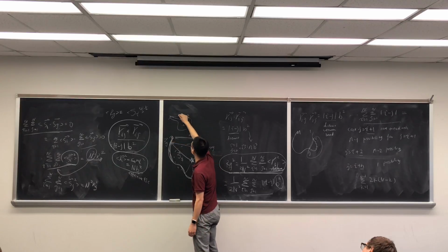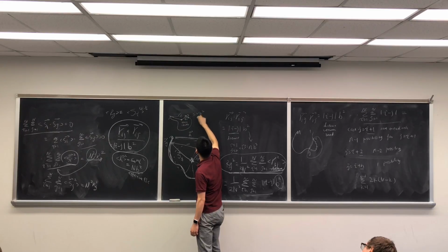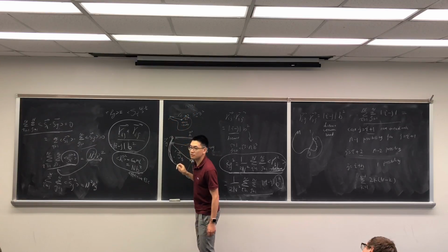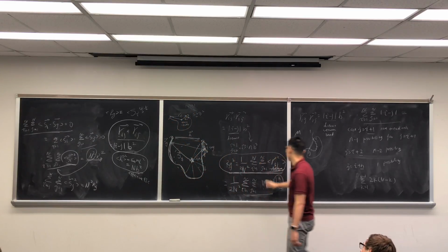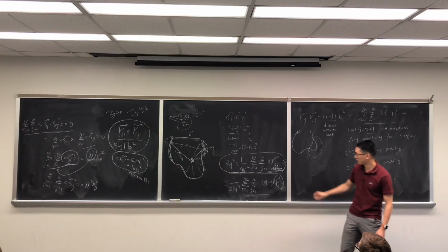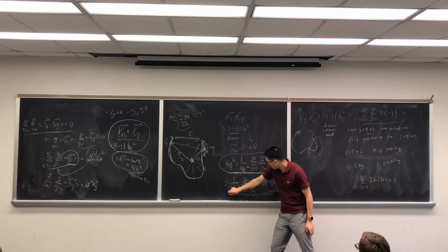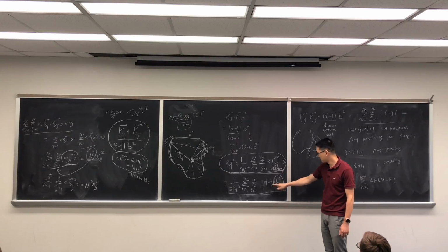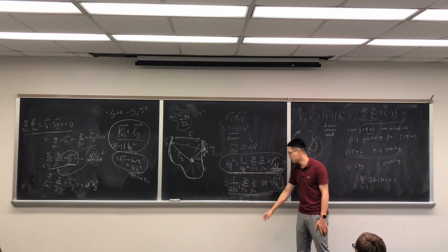So this Rij will equal n b squared, and the number of segments n is basically i minus j, the distance between these two. So if we plug in Rij equals this distance |i minus j| b squared, we get this relationship.